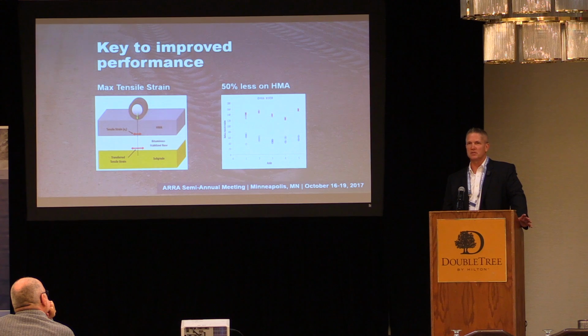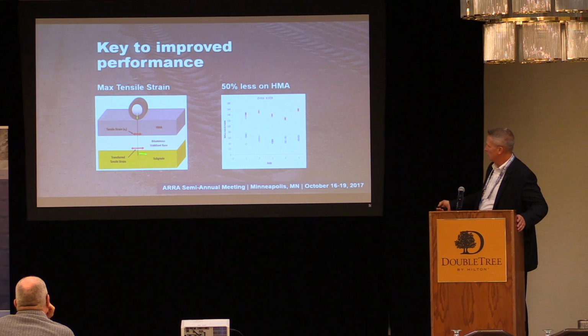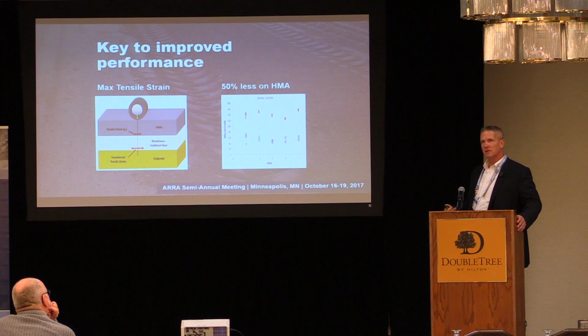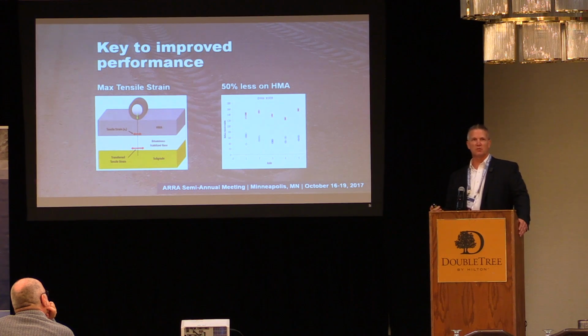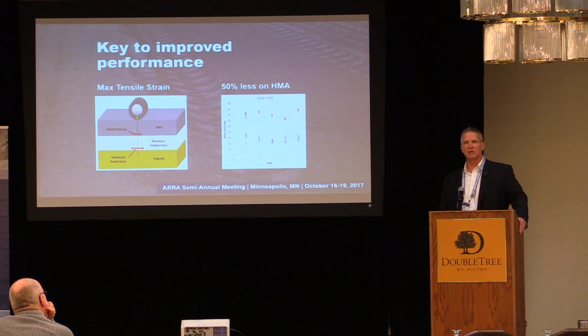And you think about that pavement section for an interstate highway, it seems pretty thin. But the whole concept there is kind of tying in from the previous speaker, one of the Andrews, is that the maximum tensile stresses are going to be driven down to the bottom of the bound layer. So when you are going in and stabilizing with a binder and creating a bound base, you're going to be driving your maximum tensile stresses to the bottom of that bound base. And through strain gauges out at Monroe, they found what happened was the strain then at the bottom of the hot mix layer was half of what that strain was at the bottom of the bound layer. So when you start thinking about the micro strains, that 70 to 200 value for perpetual pavement, and the fact that you're not getting the strains underneath that hot mix overlay that you would normally see if you didn't have a bound layer underneath it, that kind of shows you why that hot mix overlay is lasting much longer.